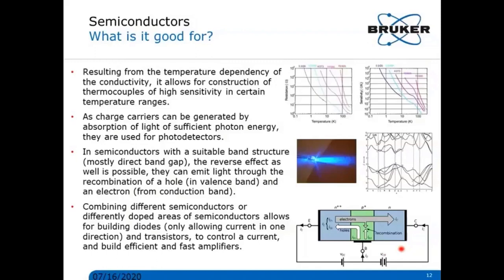And the combination of those two allows for building complex logic structures, fast amplifiers for signals, and things like that. And what Michael will later show is that we can grow those in an epitaxial way, so the whole structure would be flipped by 90 degrees, and by lithography and etching process, we can structure those, and that enables us to build processors with tens or hundreds of thousands of individual logic switches on a very small area. And with that, I would hand back to Michael to continue on the investigated materials here.